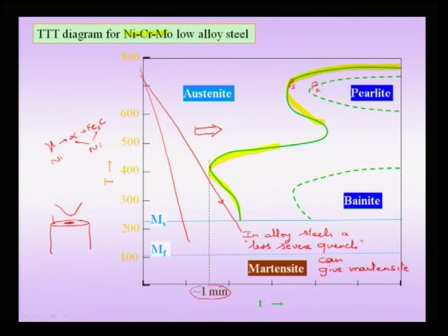So, this partitioning issue, that now my alloying element has to partition between two phases, the alpha and Fe3C, is in addition, of course, to the carbon. I am talking about 0.8% carbon gamma, then this carbon also has to partition, because alpha is very low in carbon, Fe3C is 6.67% carbon. So, in addition to the carbon being partitioned between alpha and Fe3C, now the alloying elements, and each has its equilibrium solubility in alpha and Fe3C. This is true for nickel, this is also true for chromium in the current case, and also for molybdenum. That means all these alloying elements have to partition between the alpha phase and Fe3C phase, which implies that now my overall eutectoid transformation is sluggish and my TTT diagram is to the right.